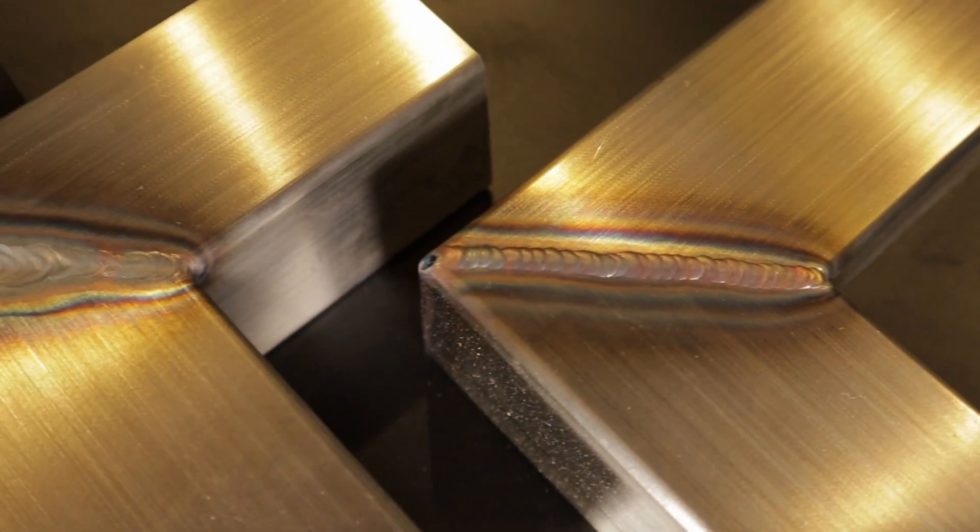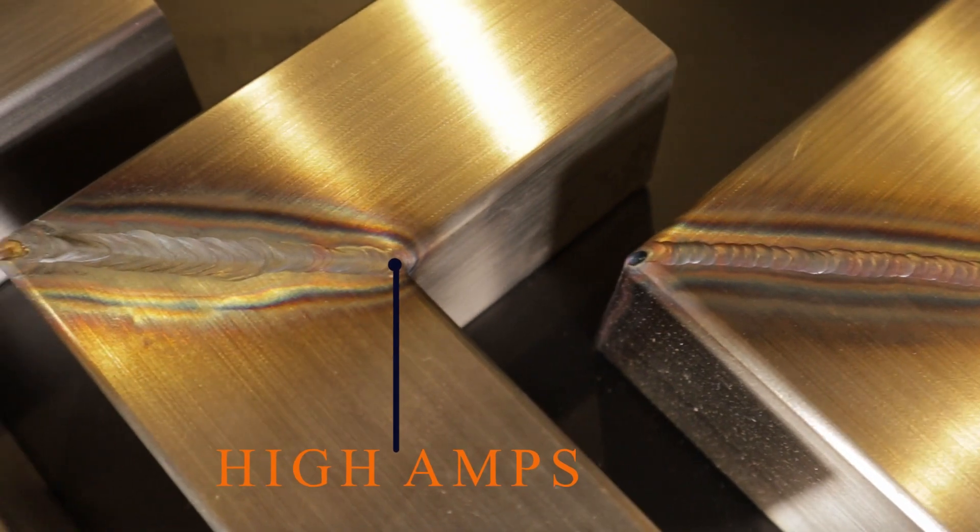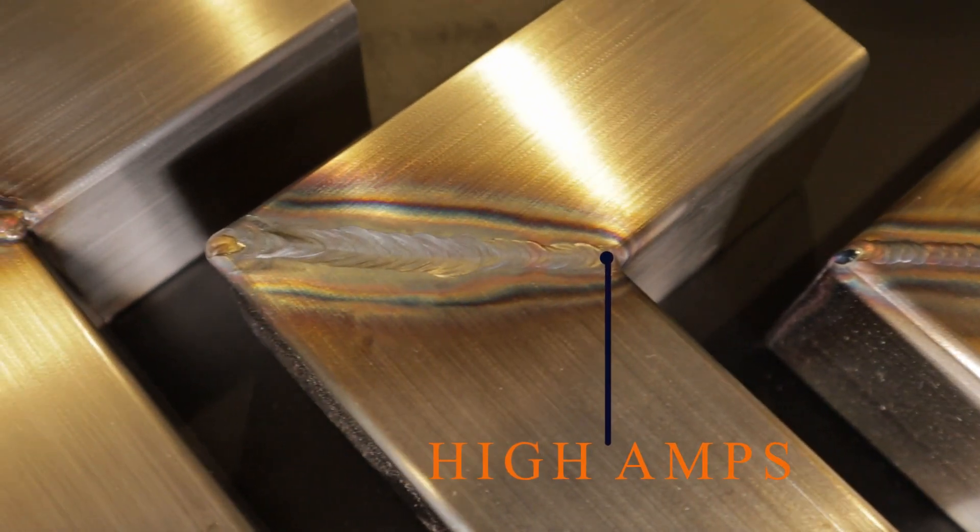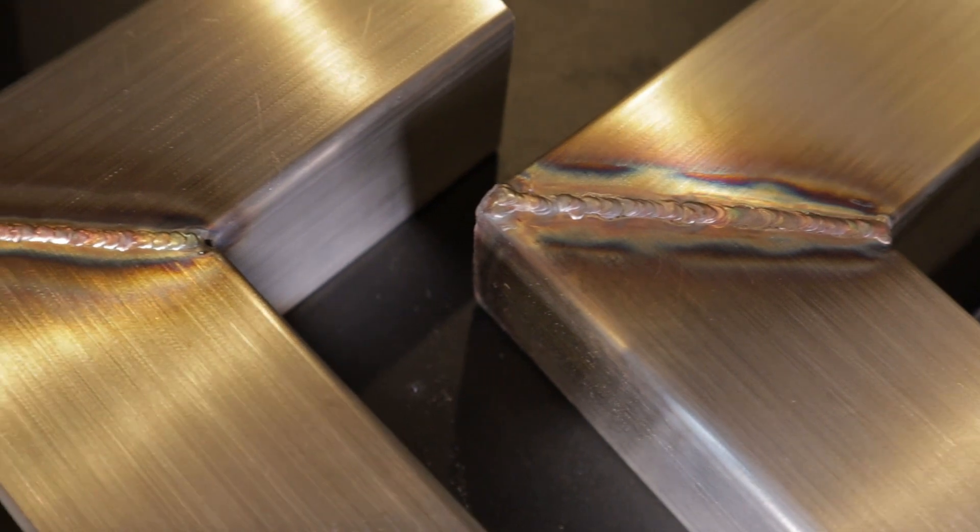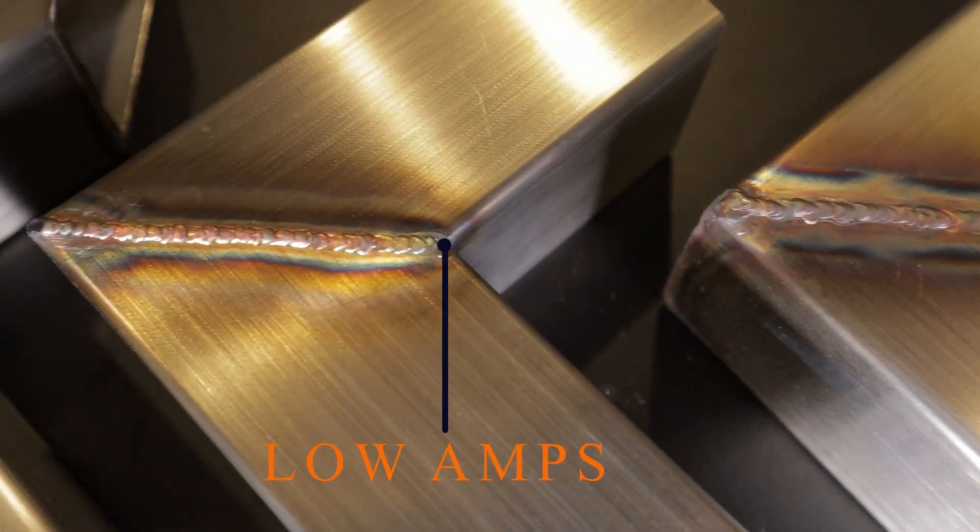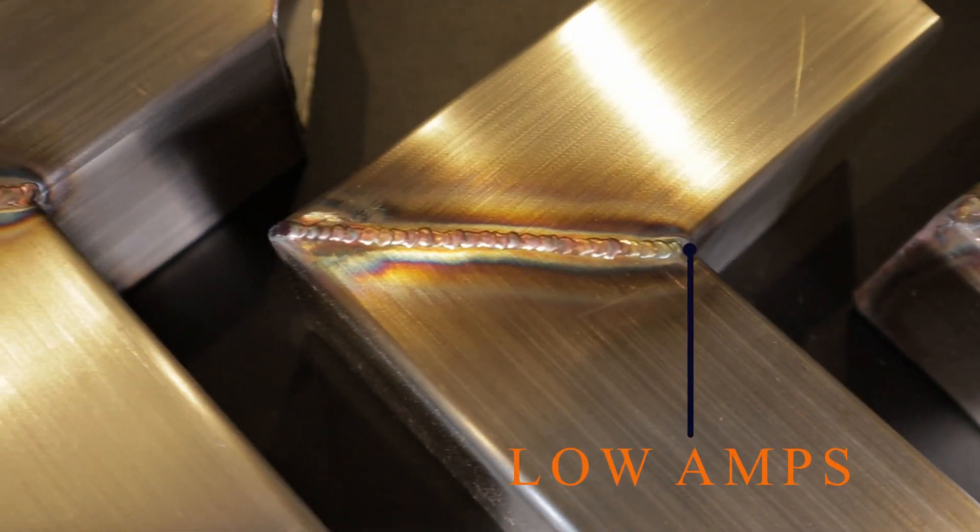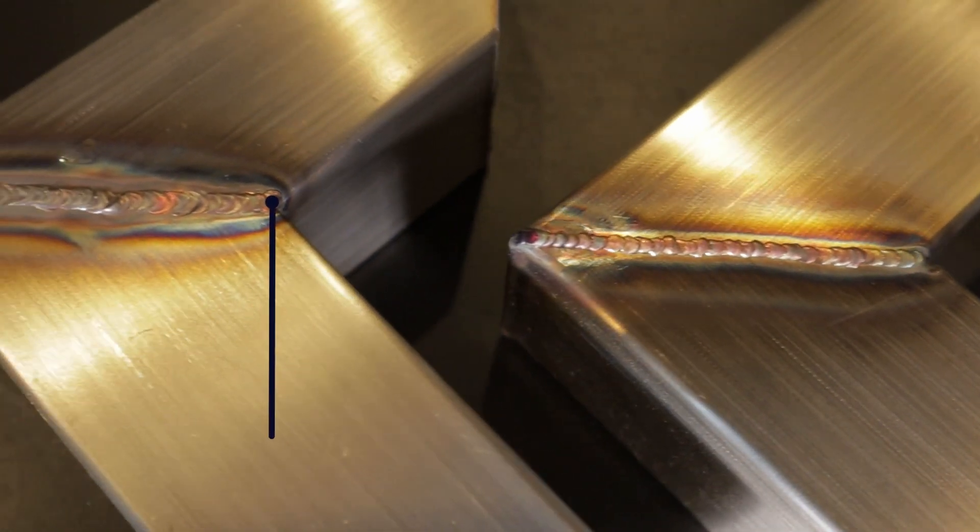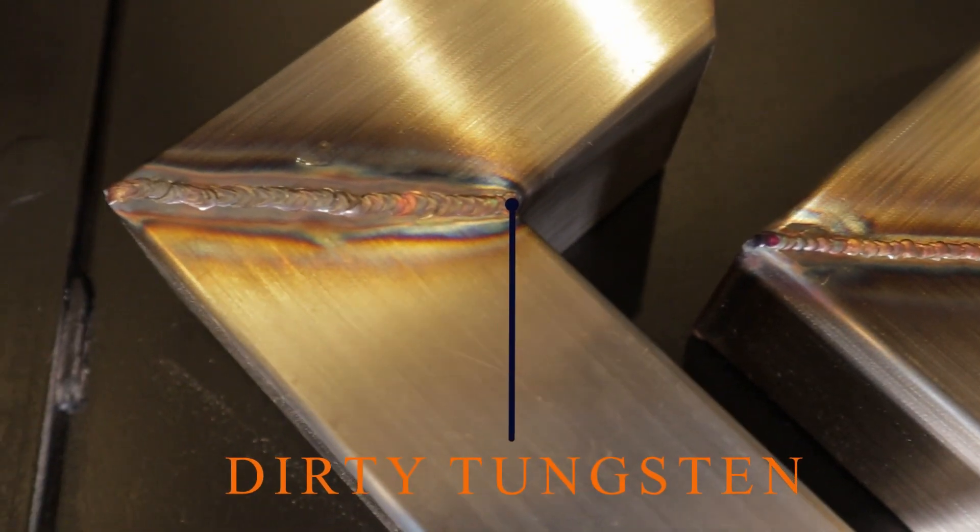The first weld is ideal with its salmon colour and heat affected zone. The second is the hot with 65 amps cooked and it's sunken. Third is the small wire with the erratic feeding. Fourth is the 25 amps which is too cold and proud weld with lack of penetration. And the last one is the dirty tungsten.